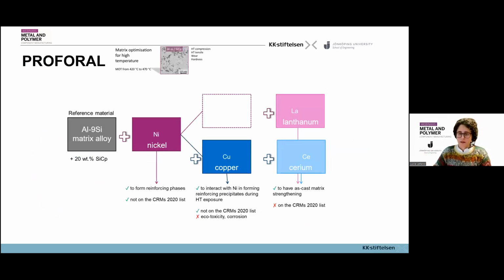So looking at the first part of the project, when we went for matrix optimization, we started with our reference material, which is the Sikalite current solution. It is an aluminium 9 silicon matrix alloy reinforced with around 20% of silicon carbide particles. And then we looked into literature to support the selection of alloying elements and improve the mechanical performance of the